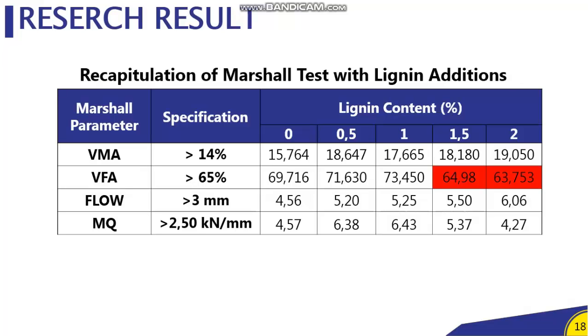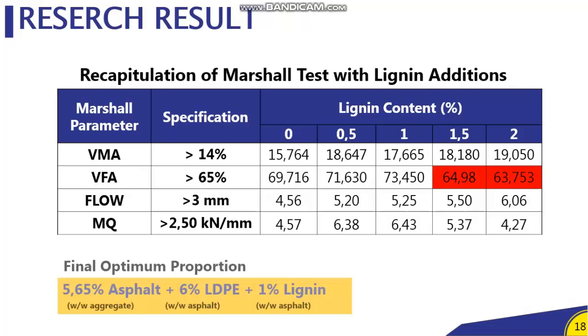There are two variables that are not recommended under the Bina Marga specification. And for the final optimum proportion, we get 5.65% asphalt weight per aggregate, plus 6% LDPE weight per asphalt, plus 1% lignin weight per asphalt.